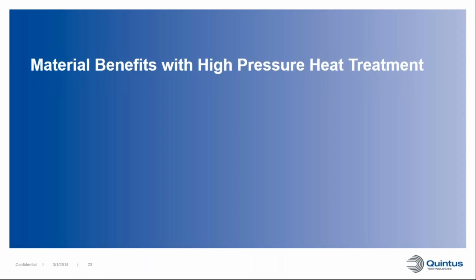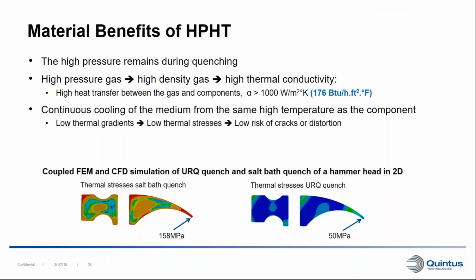We have already discussed the benefits on the process side of high pressure heat treatment, and now we will look more into the benefits from a material perspective as well. One thing to notice is that the high pressure in the HIP remains during the quenching. So we're quenching under the high pressure. Since we have this very high pressure, we also get a very high density in the gas. This gives us a very good thermal conductivity in the gas as well, which in turn gives us a very high heat transfer coefficient between the gas and the components. And this is very good because when we change the temperature in the pressure medium, the components follow closely after.